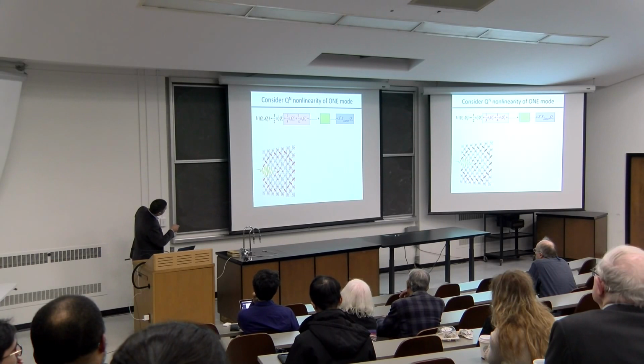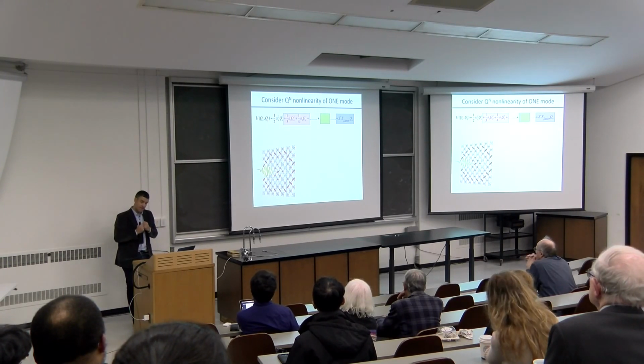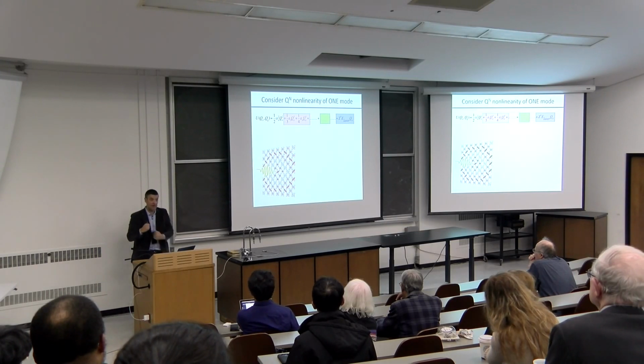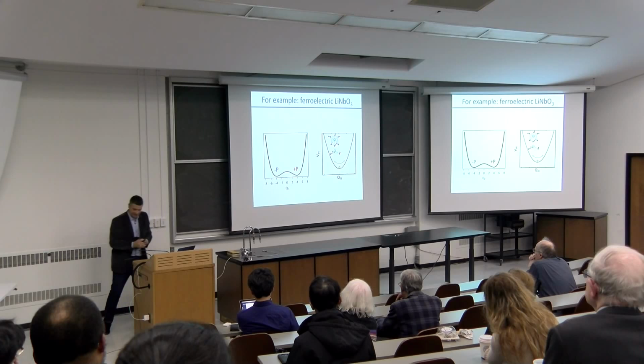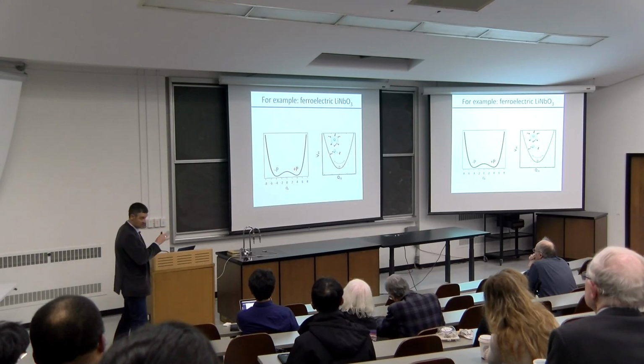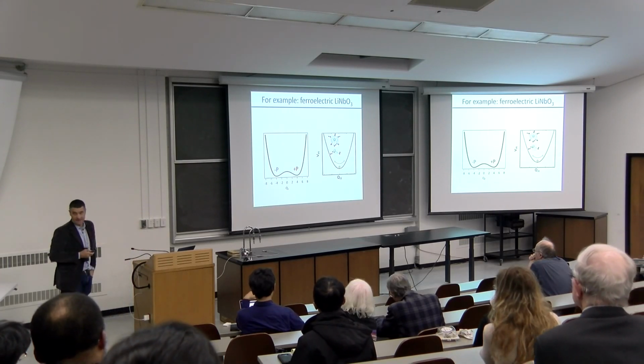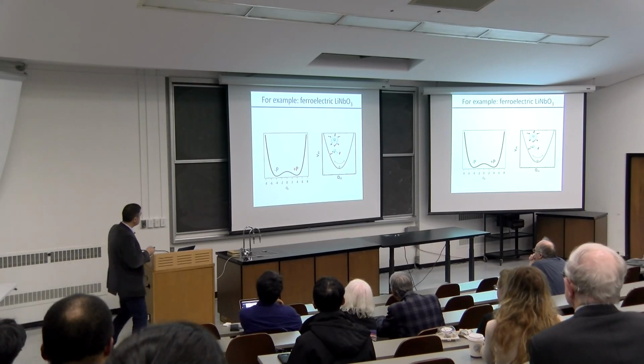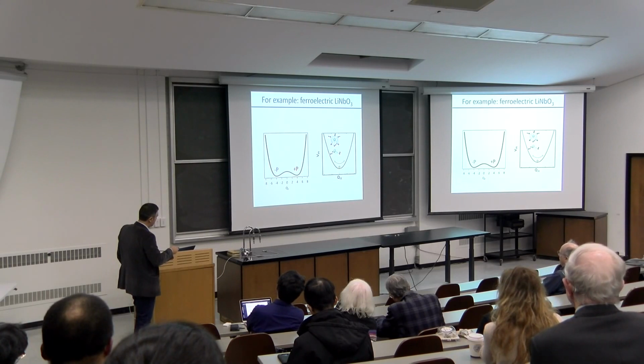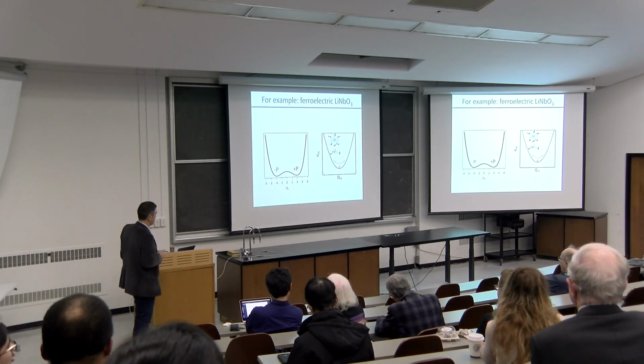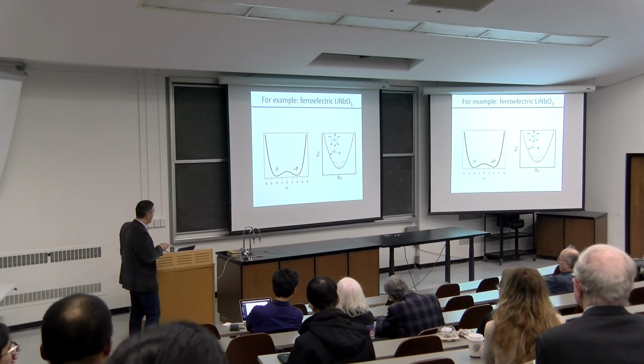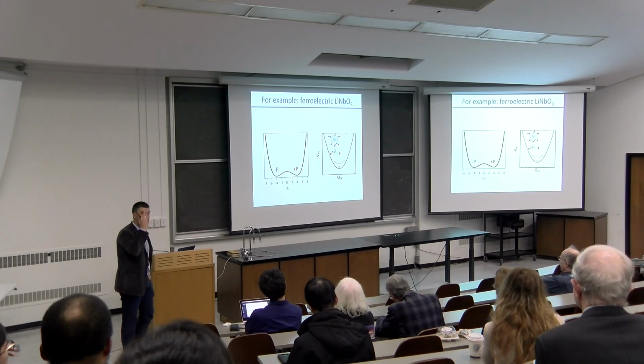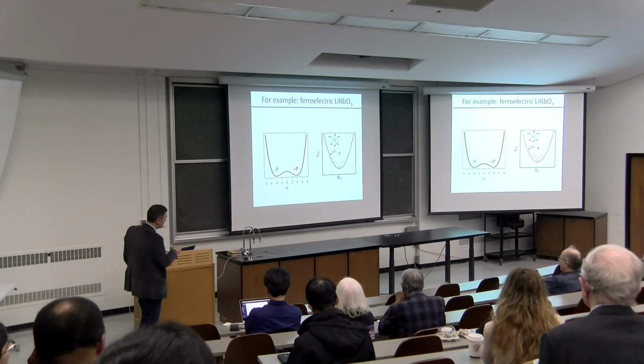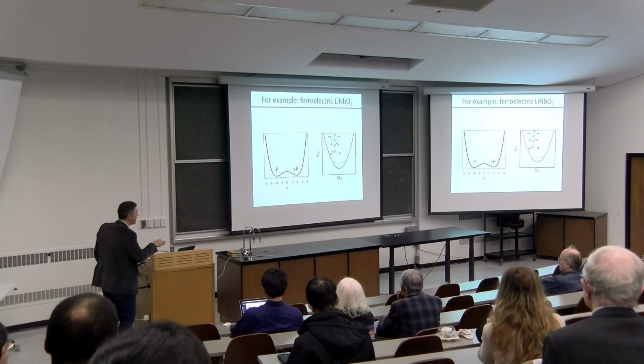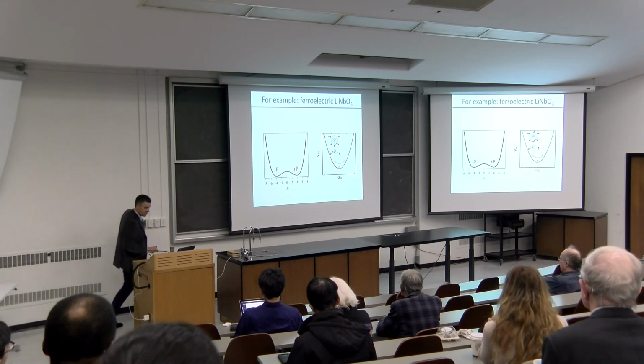So what I would like to have is a system, a material in which, let's say, the interatomic potential is highly anharmonic with respect to the motion of some atoms. So we take a ferroelectric. You can take any one of the ones you want. We take lithium niobate because lithium niobate is a material that is highly nonlinear and it lends itself to nonlinear optical studies. And as these ferroelectrics are, they have two states with different polarizations, and these are acquired by distorting the lattice along the coordinate of one specific mode, which is the well-known soft mode. What we're going to think of is not the soft mode, but another one, an ancillary mode that we drive, and we're going to look at the nonlinear phonon response of this just to demonstrate the point.